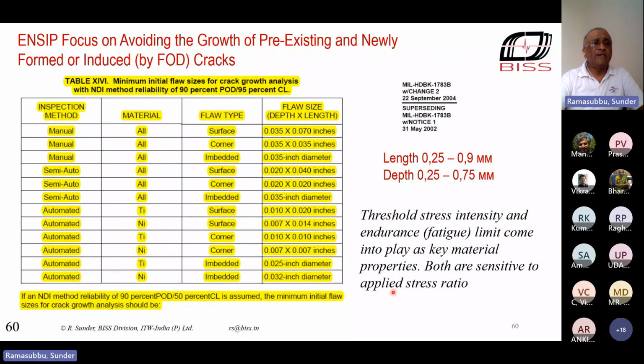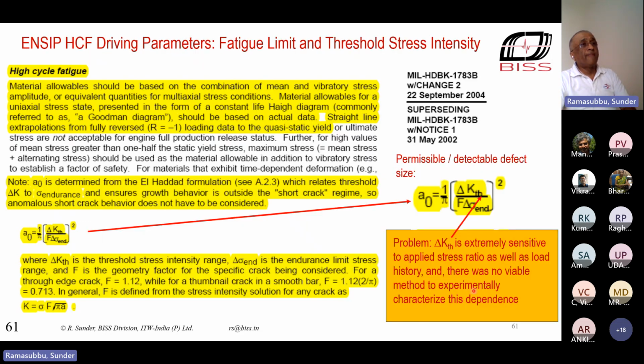And you need to look at the non-destructive inspection as well as the threshold stress intensity and fatigue limit considerations, which are not the only parameters in airframe design, but here they become extremely critical. And very importantly, both are sensitive to applied stress ratio. This has a particular connotation to us as a community in India, and I'll come to that in a moment. The ENSIP document specifies how to calculate permissible and detectable defect size. And you can see there are two important parameters here. One is threshold stress intensity range, and the other is the endurance limit.